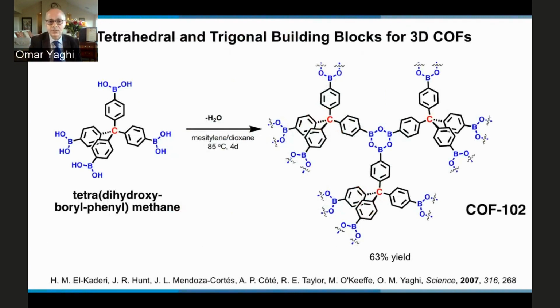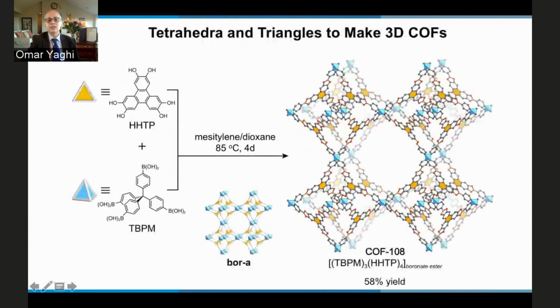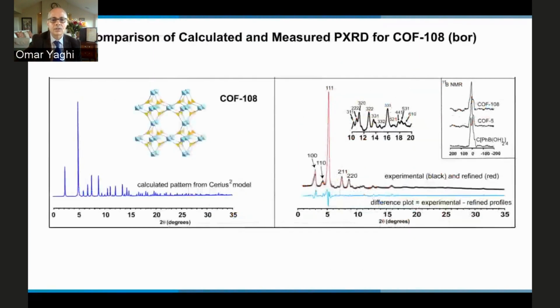One can also do this in 3D using reticular chemistry principles. You use a tetrahedral unit, you dehydrate that. Notice that the conditions haven't changed much aside from just lower temperature, and you make an extended structure made from triangles and from tetrahedra. And that happens to be this one. We call it COF 108 in 58% yield, and it's the lightest solid known to date, I guess after lithium at room temperature. So it's a very porous structure made from light elements connected by covalent bonds.